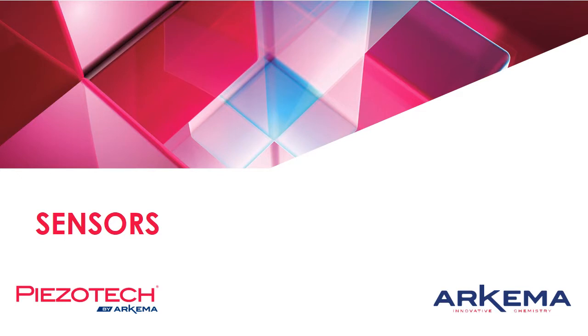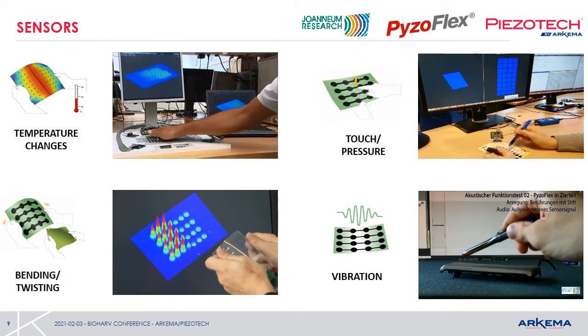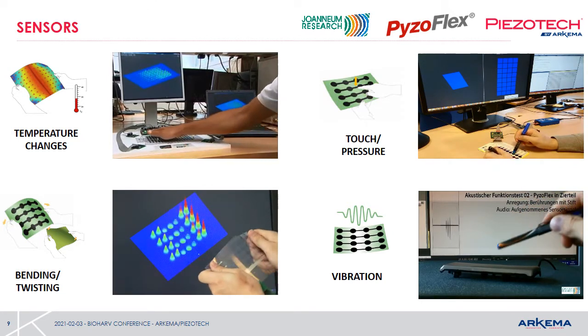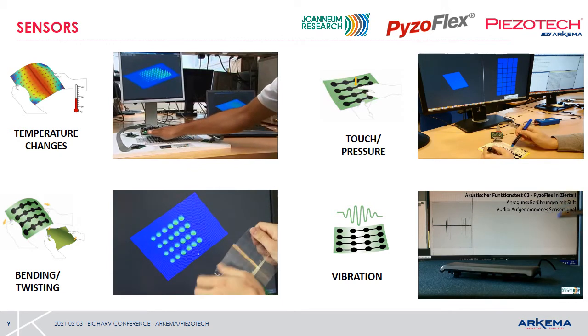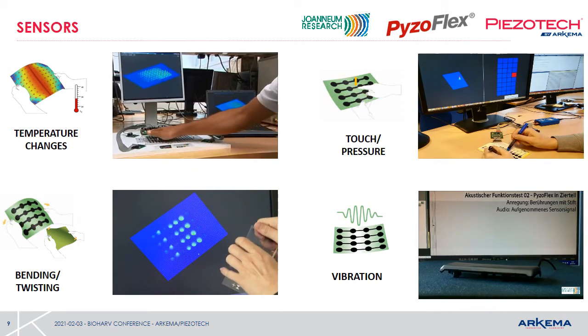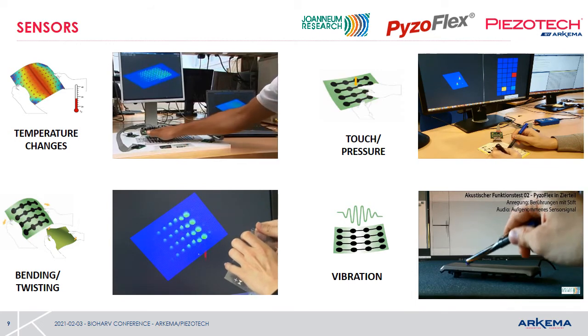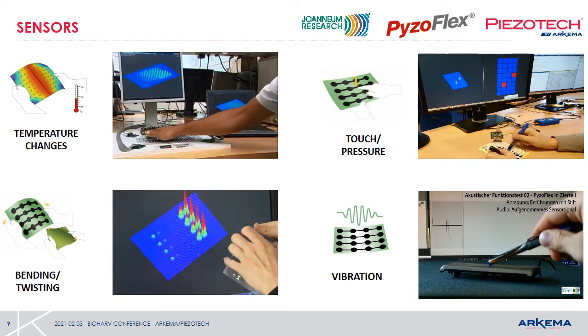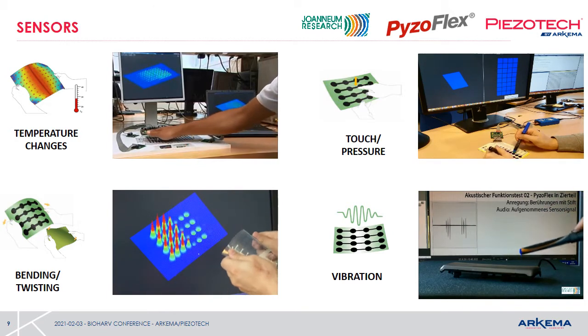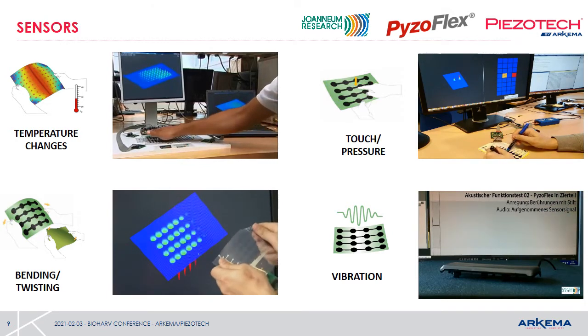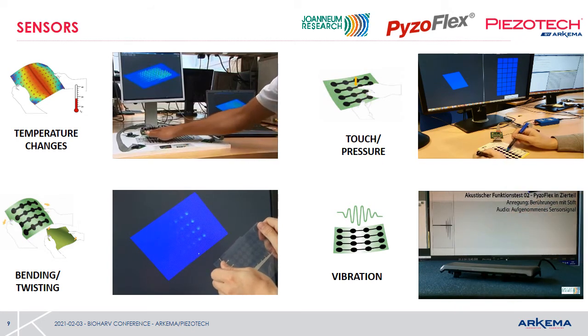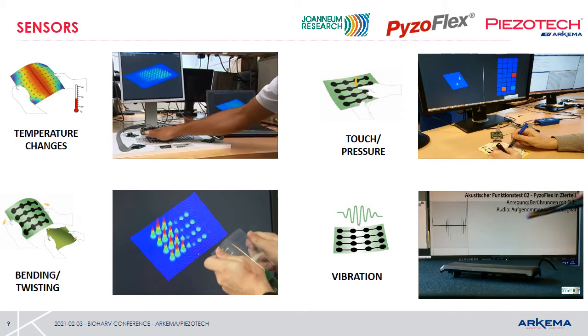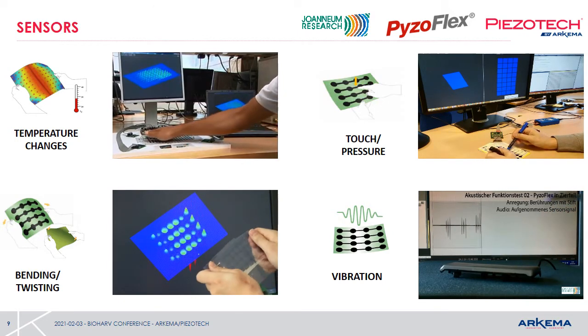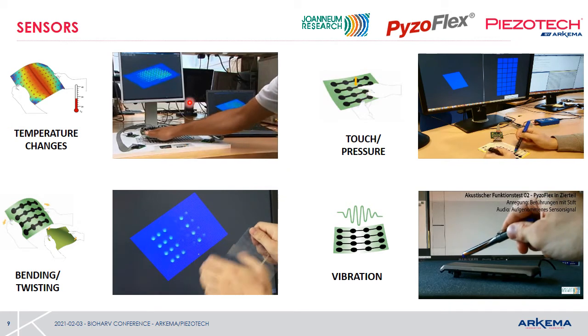So now if we jump into more applications, the first one and the most advanced one is sensors. You can use one material, for example, the copolymer 80/20, and then you can make a printed array of sensors. So the processing will probably be reviewed by Barbara later. You have a polymer substrate, you're going to print a bottom electrode, then you're going to print the piezo layer, then print the top electrode, and there you have the array of sensors. The same array of sensors, depending on the electronics that you put, is able to detect temperature variations or proximity sensors.